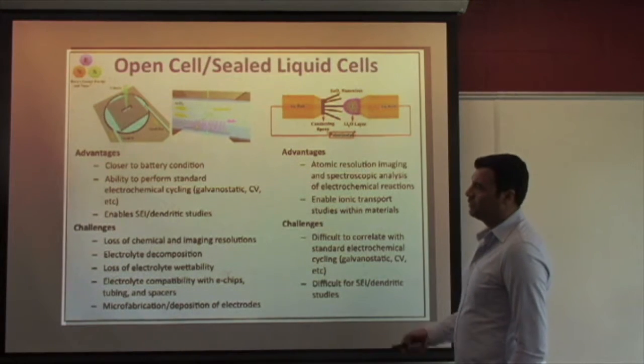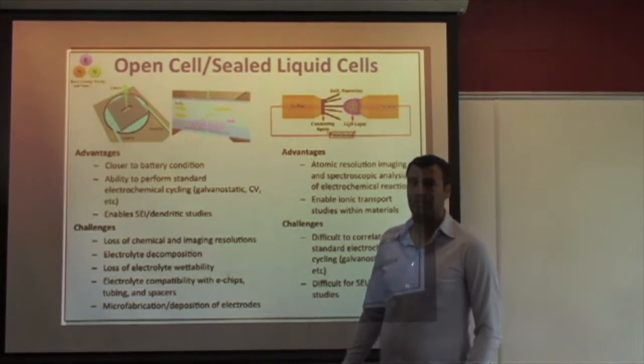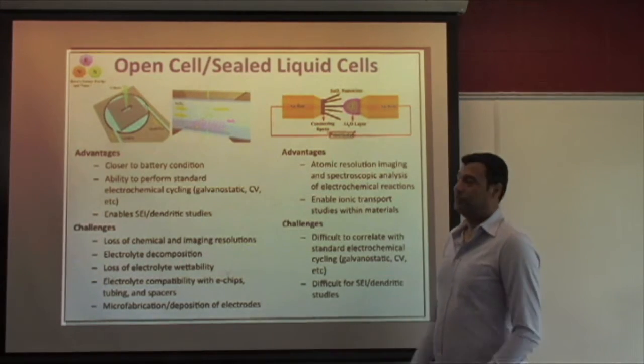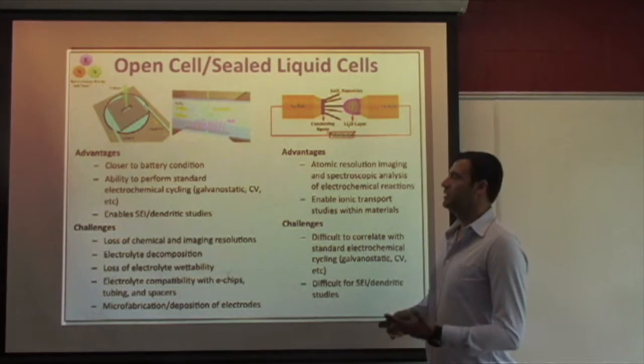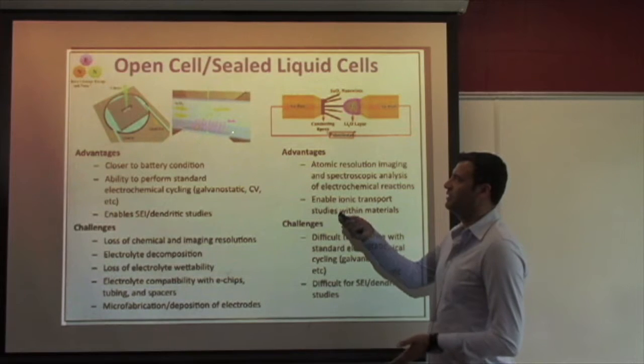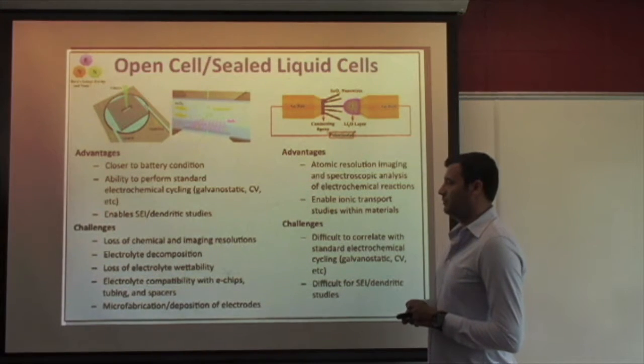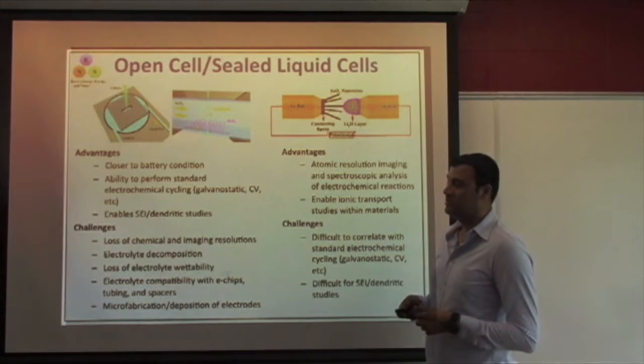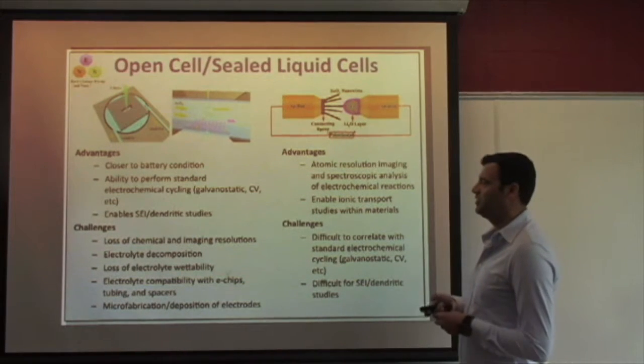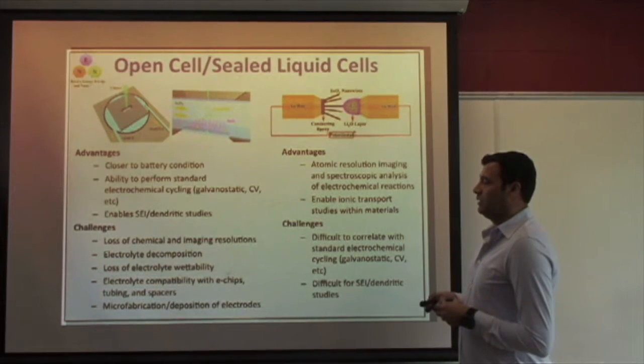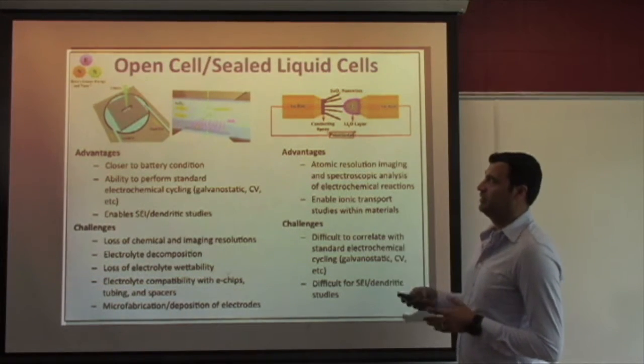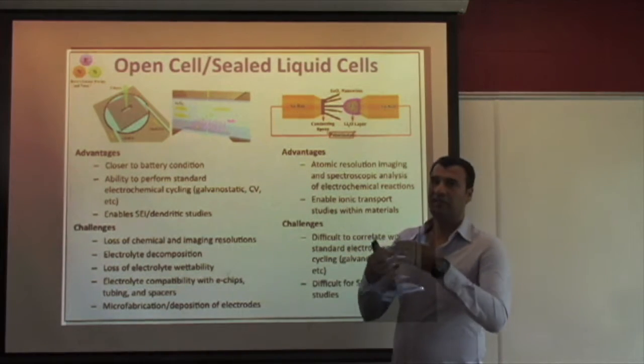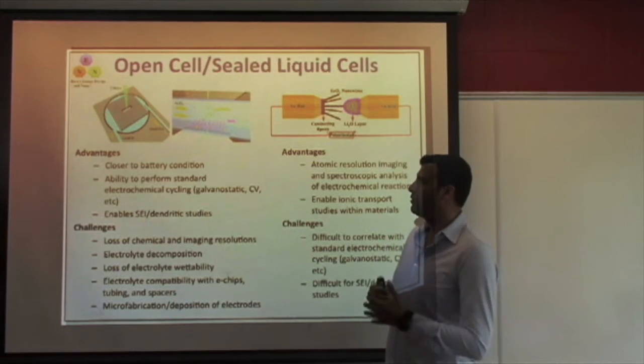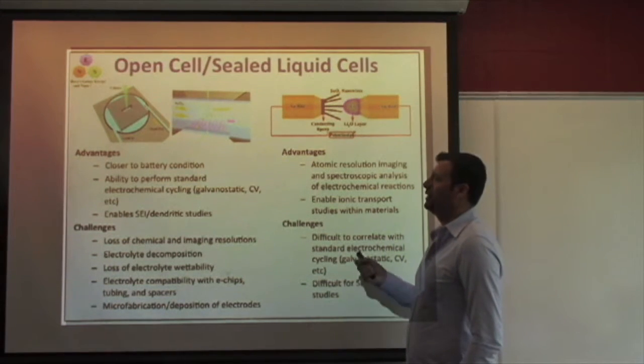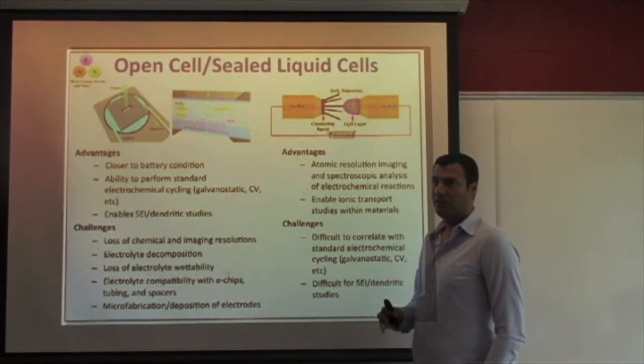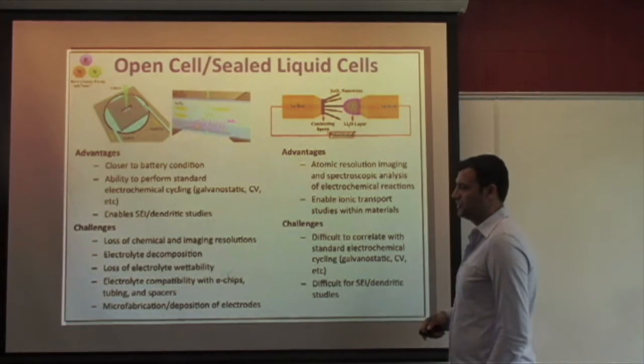If you are interested, for example, in looking into the SEI or dendritic formation, then maybe you have to have the liquid flow and the liquid configuration, and maybe that's the right system for you to use. But obviously you're going to have some sort of loss in the resolution of imaging or chemistry. You need to be worried about wettability. Sometimes the silicon nitride won't allow the liquid to nicely form a film on the surface. So that's something you need to play with, the hydrophilicity and hydrophobicity of that surface.